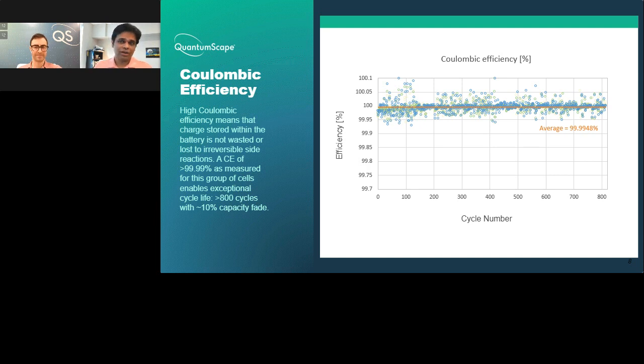But because of this extraordinarily high coulombic efficiency that is basically on par with state-of-the-art lithium-ion batteries, what this means is that you can essentially now use an anode-free configuration and still get the cycle life that you want. And so I think coulombic efficiency is really the distinguishing factor that enables either anode-free cells or whether you have to use a lithium foil to reach the kind of cycle life you want. Of course, lithium foil is expensive, but lithium is also not very dense, which means that you take a hit on the volumetric energy density, as well as a little bit on the gravimetric energy density. So coulombic efficiency is one of the key enabling factors to enabling an anode-free cell.